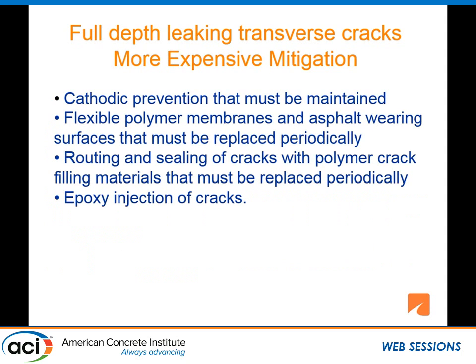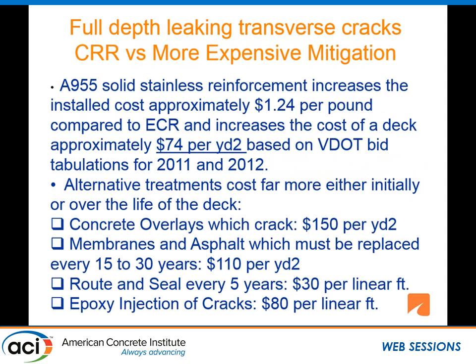What are some other strategies that folks use today? Cathodic protection is something you have to maintain. You have to have a competent electrical staff to maintain the cathodic protection systems. Polymer membranes can bridge over these cracks, but you have to deal with replacing the asphalt surface periodically, replacing the membrane. You can route and seal the cracks. You can inject them with epoxy.